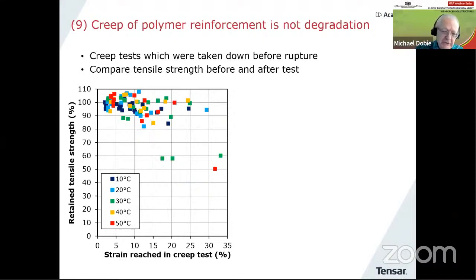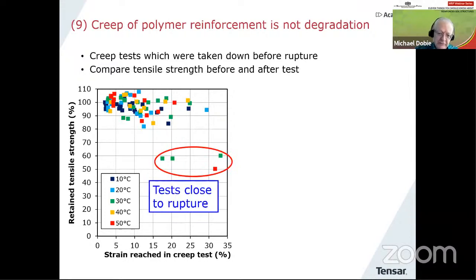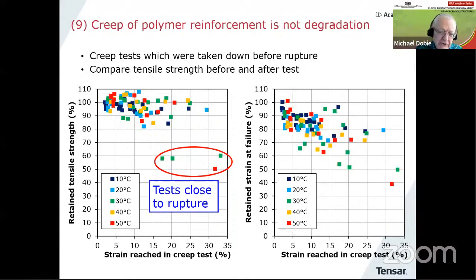Now, what you can see for the majority of the data, it's around about 100%. This means you take down a specimen after, say, 5 years. It's been resting there with a high load on it, and you measure its tensile strength using a fast test, and that strength remains the same, and that's the residual strength. There are some points here which were close to rupture, and they had dropped down in terms of their tensile strength. What's affected more than that is the retained strain at failure.